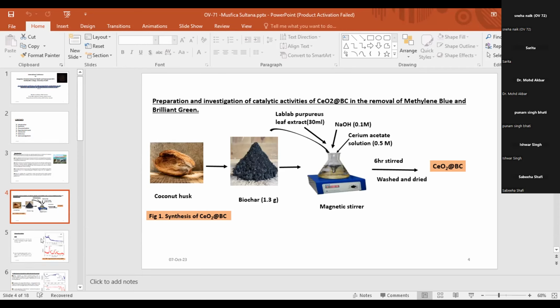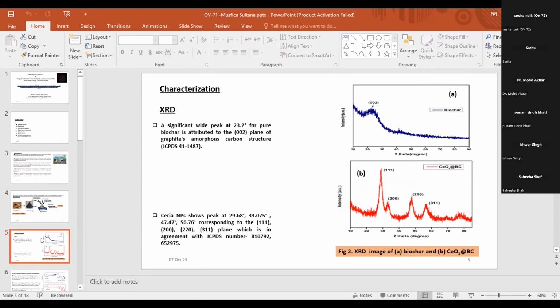This cerium oxide biochar I have characterized with various techniques. First of all, with XRD. When raw biochar is taken, a significant peak at 23.2 degrees 2 theta appears because of the graphitic and amorphous carbon structure. For the cerium oxide biochar, it shows peaks at 29.68, 33.07, 47, and 56 degrees. These peaks match well with the JCPDS number. So from the XRD data, we confirm that the formation of cerium oxide biochar has taken place.